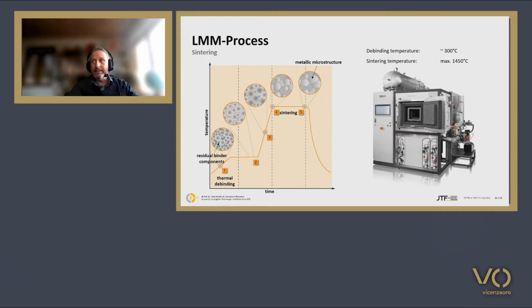You basically burn it. And then because of the thermal expansion, your powder particles get into contact because of the high surface energy. When heating further up, they build sintering bridges, and in the end, they build a fully dense microstructure. And that's a procedure that's completely well known from metal injection molding. So basically, the process is like metal injection molding, but instead of making your green part with an injection molding machine, you print your green part with this newly developed printer.